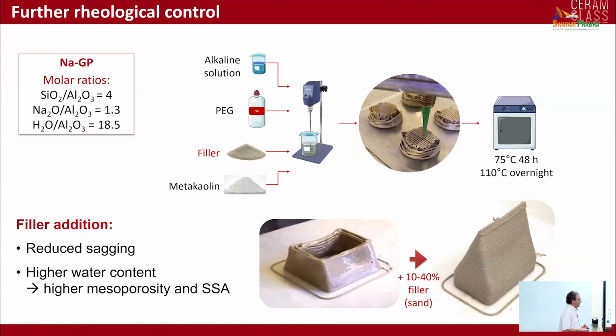So we realized that despite having this rheological additive, we still had issues in terms of the yield strength. And bear in mind that we were the first ones in the world to carry out this work, so we couldn't rely on other people's experience. And so we started adding some fillers, for instance, sand, in order to increase the yield stress. And you can see that in this way we can control the sagging of the structure for inclined planes.